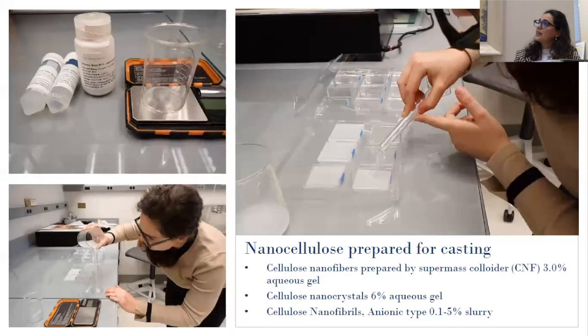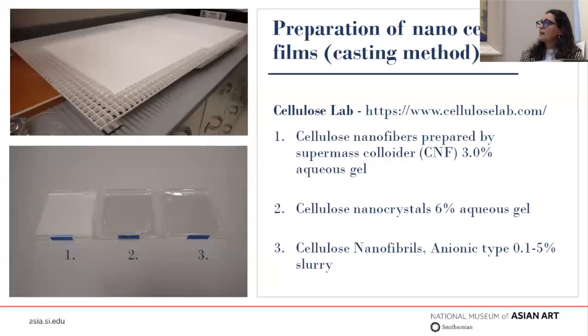Next slide, please. So for the aqueous gel, 3 different samples were given to us to be tested by a Canadian supplier, and they came in different formulations as aqueous gels. As you can see, we prepared the film with all 3 different aqueous gels, but after creating the film with the casting method, we decided to proceed to test only the first typology, because it was the only one that presented an appearance that was possible to use for our purpose, that was to find the support for repairing parchment. The other 2 aqueous gels, after creating the film with the casting method, looked very brittle, and they had a plastic appearance, so they were not useful for our purpose.